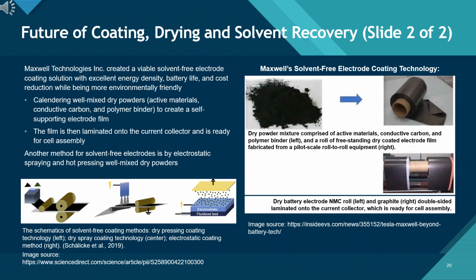This film is then laminated directly onto the current collector, eliminating the need for slurry preparation, drying ovens, or solvent recovery systems. The result is lower manufacturing cost, improved sustainability, and competitive energy density and cycle life. Additional solvent-free approaches include dry spray coating and electrostatic powder deposition, followed by hot pressing, which similarly avoid the high energy burden associated with NMP evaporation. Overall, these technologies represent a major step toward greener, faster, and more cost-efficient electrode production.